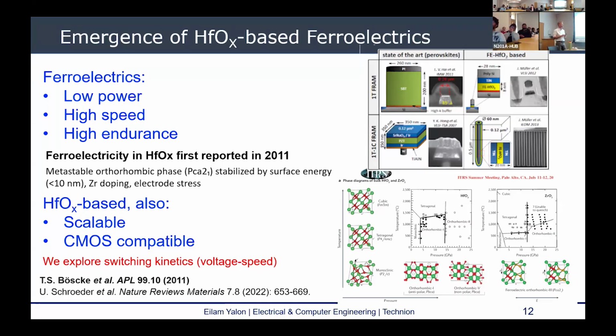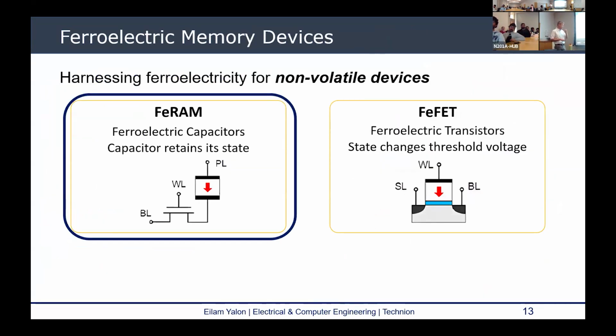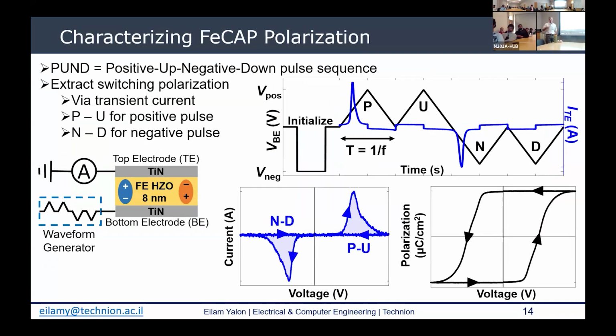And within that research, what I would like to show next is some studies of the switching kinetics, the relation between voltage and speed of these ferroelectric devices and materials. There are various ways to use the ferroelectric material in a device. The two that I will show are ferroelectric DRAM, which is essentially a ferroelectric capacitor connected to a transistor. So it's similar to the DRAM structure, but with a ferroelectric capacitor instead of just a dielectric capacitor, so this is a non-volatile memory element. And the other one is the ferroelectric transistor, which I will discuss later. To characterize ferroelectric capacitors, this is an example of metal-ferroelectric-metal: titanium nitride, hafnium zirconium oxide, 8 nanometers thick, titanium nitride.